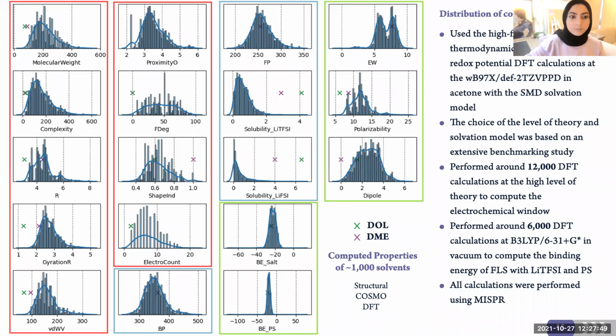And for many of these properties that are calculated, we can see that there is a broad range of values predicted. For example, molecular weight, you can see the gyration radius, flash point, and boiling point. There is a wide range of values for all of these properties. But we can clearly see that the solubility of lithium TFSI and lithium FSI in these solvents are much lower than that compared to the DOL and DME, which is expected to happen.